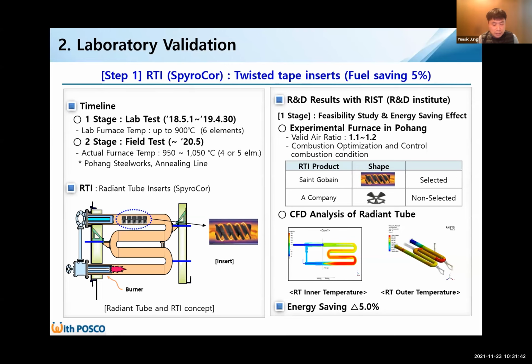During the lab test, feasibility and energy saving effect were verified. We can optimize the combustion air ratio to 1.1 to 1.2 typically. 2 types of inserts were examined. As a result, the Saint-Gobain product was selected according to the better energy saving effect. In addition, CFD analysis of the radiant tube was performed as the following features. As I told you, we found its energy saving effect is 5%.